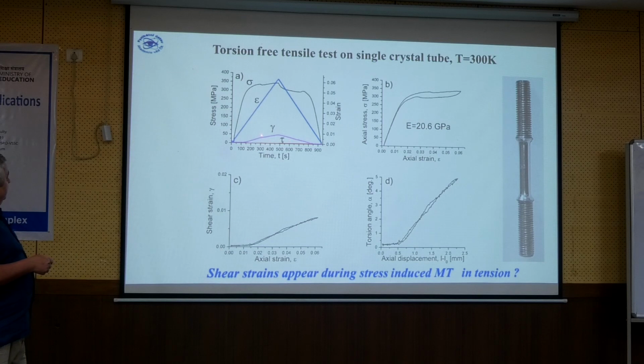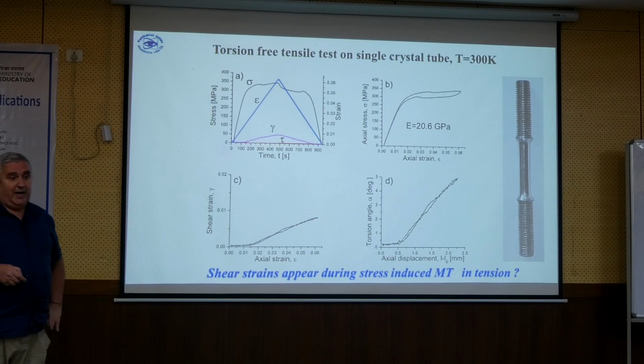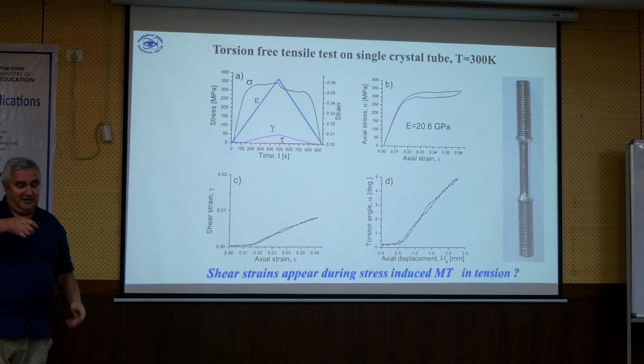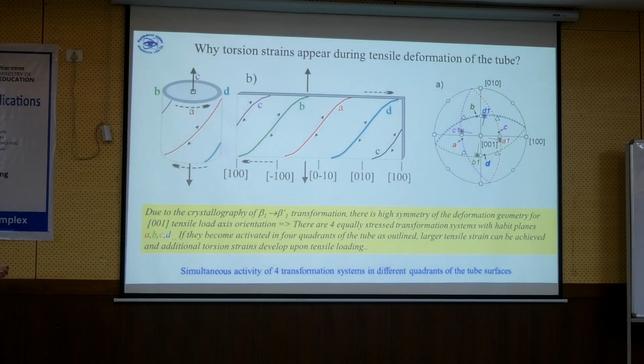And then in the very first experiments which we did, it was just deformed in tension. So when I deform it in tension, suddenly the shear strain started to appear. And quite significant torsion angle, like 5 degrees, which was never observed on any plastic material. And if you unload, it went back. It was a complete puzzle. Why, if you pull, will it start to rotate? So we were really thinking about it, and again, it's a problem of this strain-compatible interface.